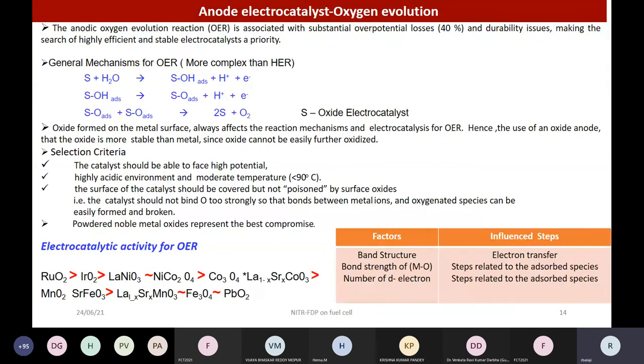People will prefer iridium oxide, because iridium does not have a tendency to undergo oxidation beyond the plus 4 state, and it will be stable even if you operate at higher voltage or higher current density. That's why iridium oxide is the preferred electrocatalyst for the oxygen evolution. In a few cases, to increase the efficiency further, if you are confident with an operating voltage lower than 1.8 volt per cell, you can go with ruthenium oxide electrocatalyst. But it is advisable to use a mixture of ruthenium oxide and iridium oxide, and you will end up with very low voltage loss on the anode side.